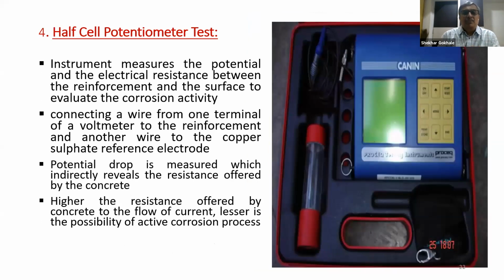The fourth test is the half cell potentiometer test. This is an instrument which measures the potential and the electrical resistance between the reinforcement and the surface to evaluate the corrosion activity. Here a wire is connected to one terminal of the voltmeter and to the reinforcement, and another wire to the copper sulfate reference electrode. Potential drop is measured, which indirectly reveals the resistance offered by the concrete. The higher the resistance offered by the concrete to the flow of current, the lesser is the possibility of an active corrosion process. So based on that, we can predict the probability of corrosion. It will not give the extent of corrosion, it will give the probability of corrosion.